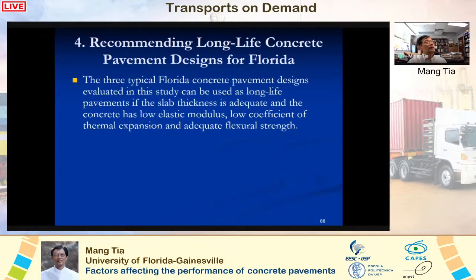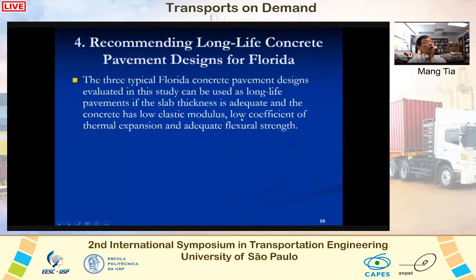Okay, so here's our recommendation to Florida DOT. The 3 typical Florida concrete pavement designs evaluated in this study can be used as long life pavements if the slab thickness is adequate and the concrete has low elastic modulus, low coefficient of thermal expansion, and adequate flexural strength. So the key thing is not just flexural strength, but we need to have low elastic modulus and low coefficient of thermal expansion.